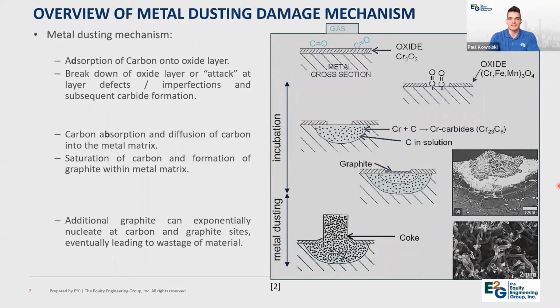So a brief schematic or summary of the actual mechanism of metal dusting. So again, first, a high temperature carburizing atmosphere is required. So we'll see how here on the schematic on the right. In this case, it's carbon monoxide, again, which we may find in syngas. It attacks the material, or specifically attacks the oxide layer, and preferentially will go to areas of cracking or imperfection or defects in the oxide layer, and it adsorbs on the surface. So basically the carbon is sitting on the surface.